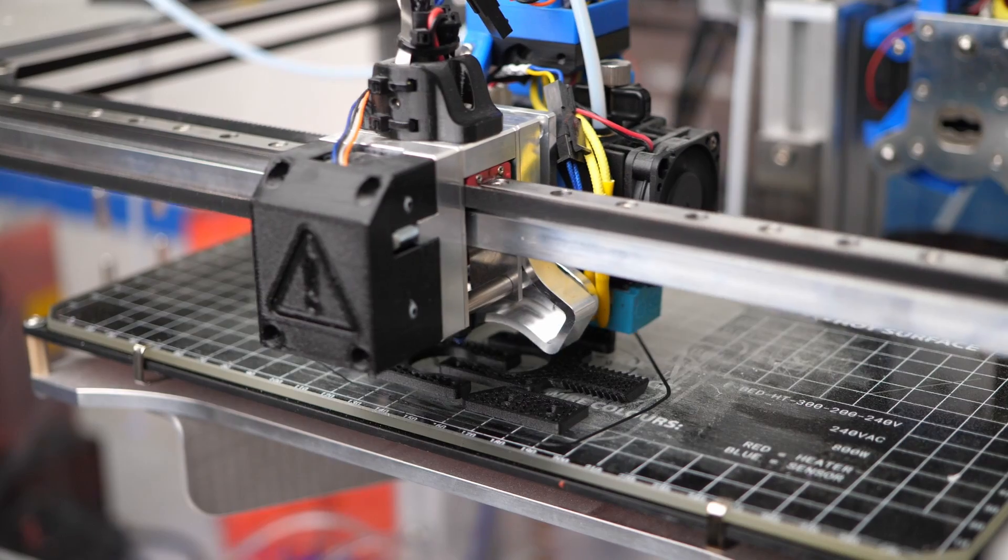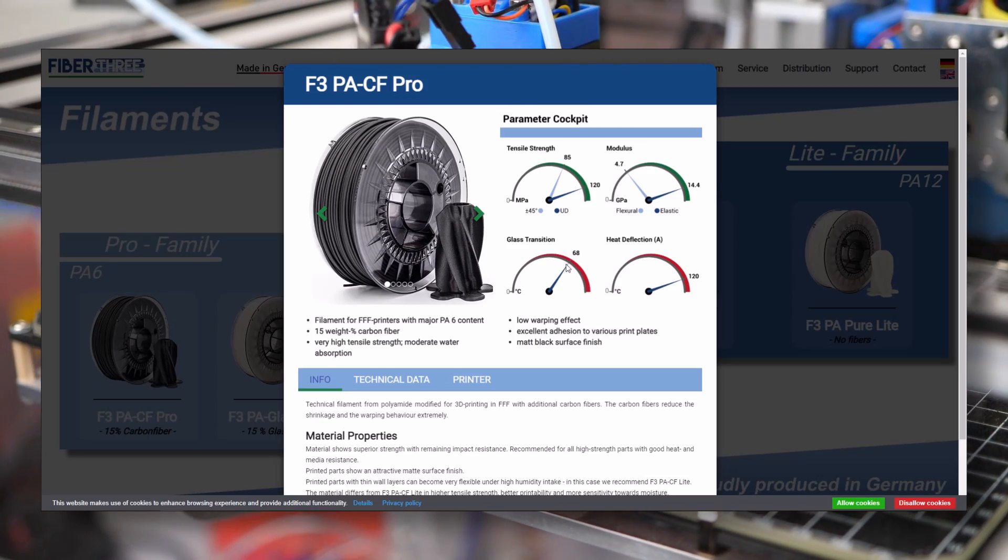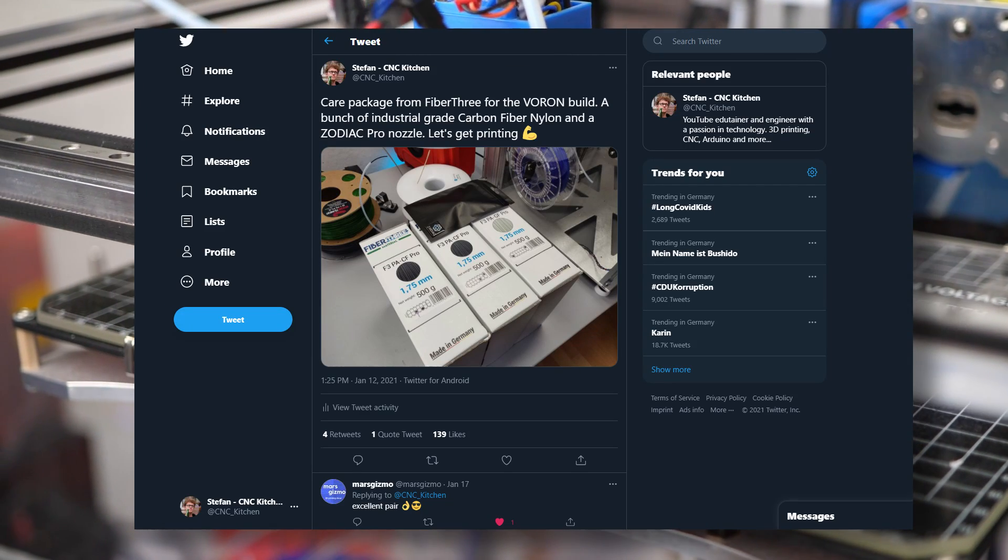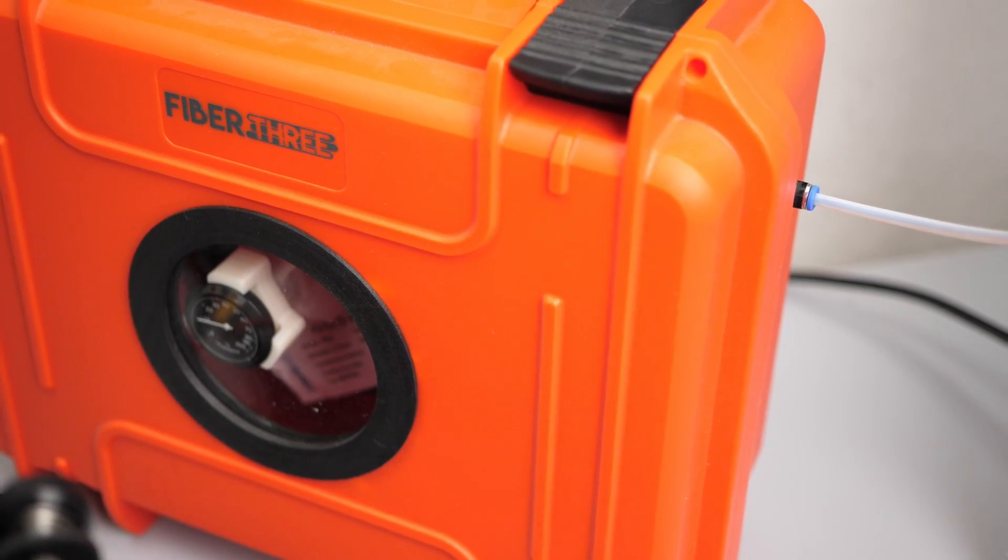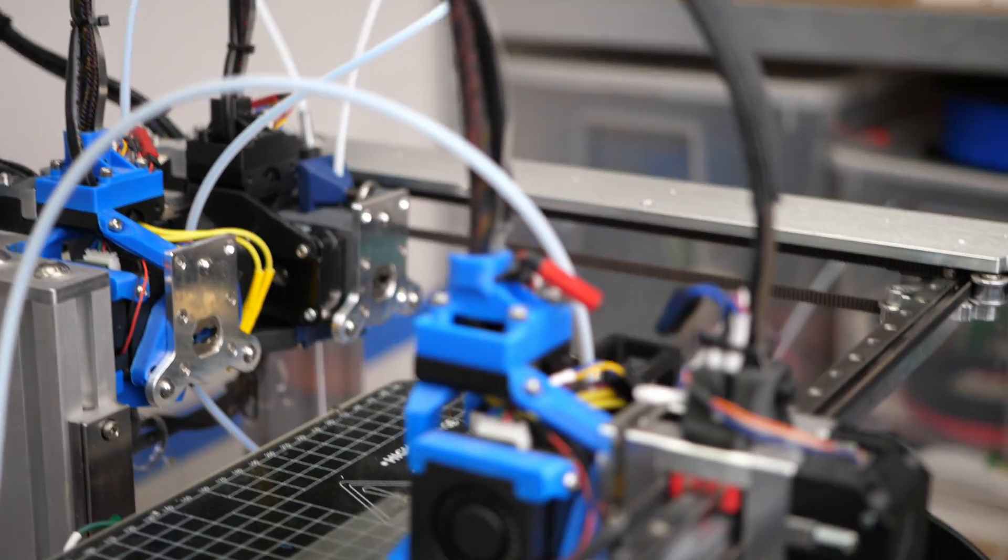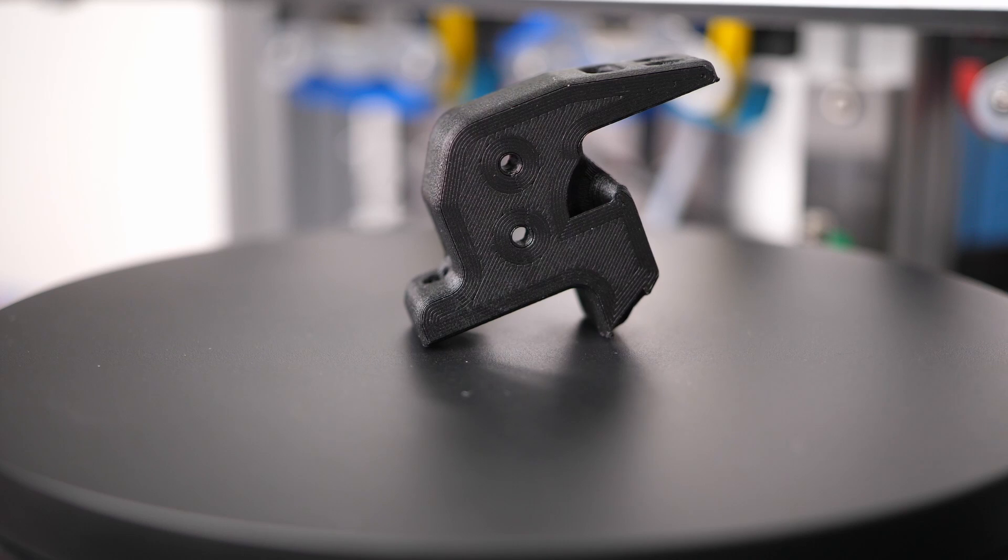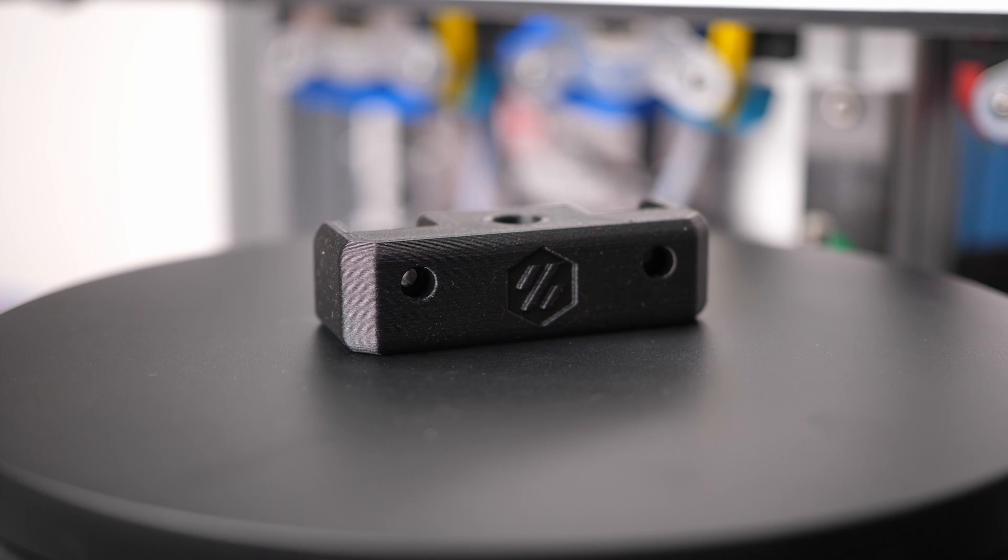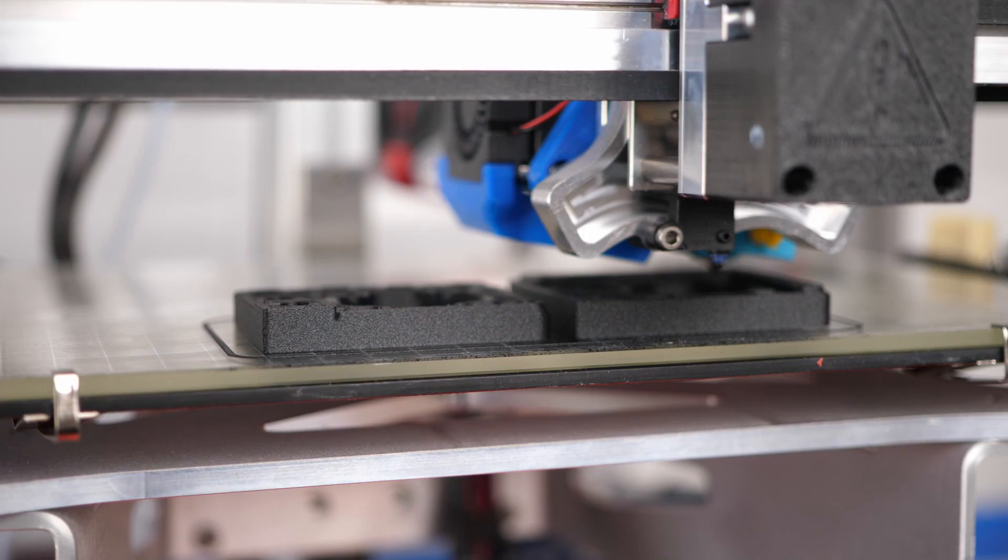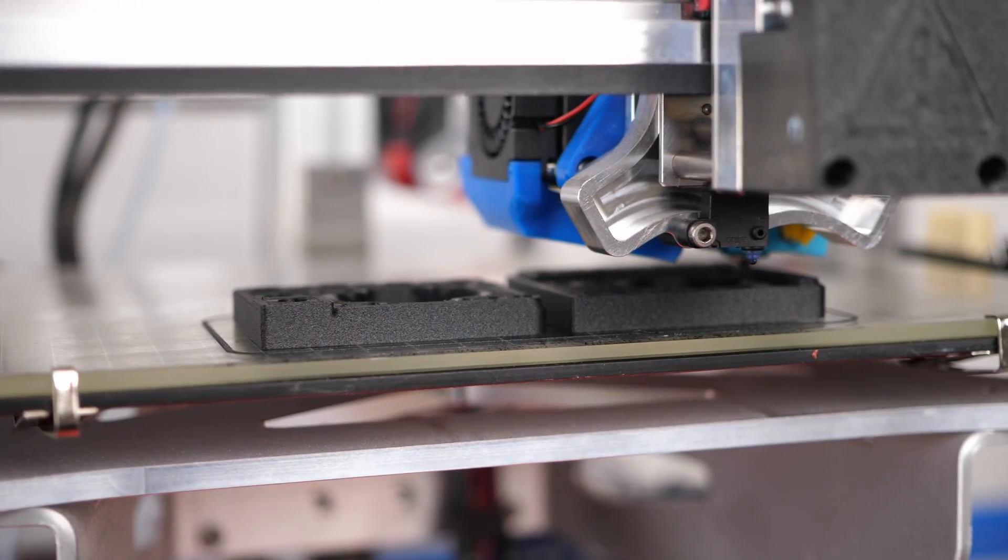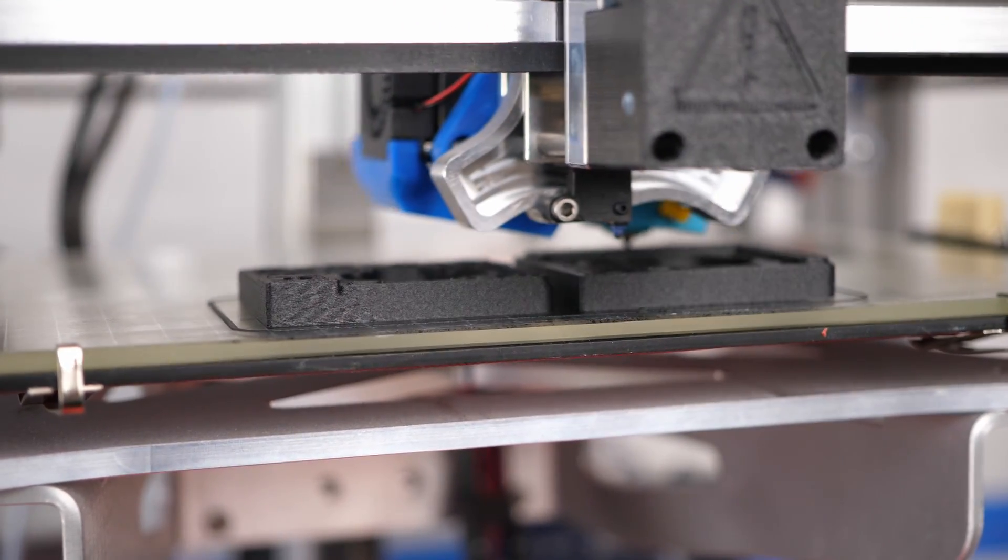So, as I said previously, I was looking for a really stiff setup and the carbon fiber nylon from Fiber3 that I used is more than 5 times more rigid than ABS. Felix from Fiber3 very kindly provided a bunch of their PACF Pro material for the build. Since I still had more than 2 years old rolls of the same material around, I thought I'd save the new ones and printed the parts out of leftovers, which will haunt me really badly soon. The Voron parts are designed beautifully and printed without any supports. I used 4-5 perimeters for the parts and 60% infill to make them strong. Carbon fiber nylon prints so great and if you keep it dry, so easily. Even though pure nylon might be a pain to print, as soon as you add chopped carbon fibers to the mix, most filaments barely warp anymore. Think about that when you next time see somebody print really high-performance polymers like PEEK or PEI in the even cooler form with carbon fibers. That's often not primarily to add strength, but it's often just used for making it properly printable.